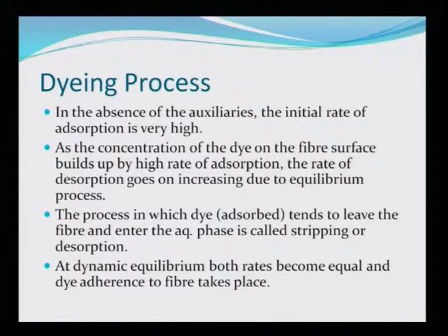The process in which dye adsorbed tends to leave the fiber and enter the aqueous phase is called stripping or desorption. So, these two processes, which are actually going in opposite directions, one is the dye entrance and the other is the dye stripping or desorption, are taking place simultaneously, and because of that an equilibrium is established. Therefore, it is important to see that this equilibrium moves in the forward direction rather than in the backward direction. Otherwise, all the dye that has been taken up by the fiber will be desorbed or stripped off by the fiber.